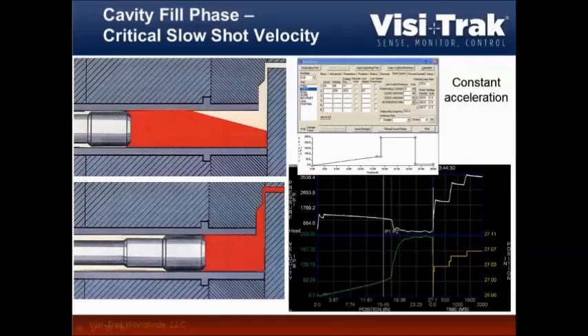Now that is especially important if we look at vacuum die casting, like in structural die casting. Nowadays, very important, we want to have the two-stage vacuum system. We have one vacuum on top of the die, like we've always had, but an additional vacuum line coming into the shot sleeve, so we evacuate from the very beginning.